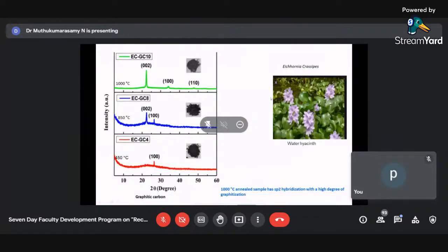And you can see we collected the leaves of this water hyacinth plant and we cut them into small pieces, dried them, then we burnt them, then we got the burnt one which we annealed at different temperatures, and at a calcination temperature of 1000 degrees centigrade also, we got graphitization there, and we got actually very good carbon. We can even say a carbon with a high degree of graphitization, and we used it as a hole transporting material in our fabricated solar cell. We also mixed it with the perovskite material and used it for the solar cell fabrication. So these are some of the images corresponding to that material.